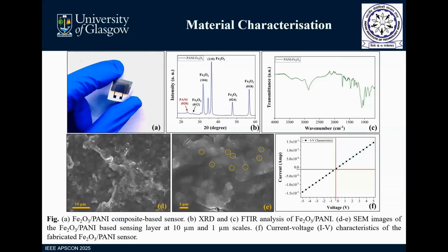In figure A, we can see the original optical image of our sensor. You can see the green part is the electrospun PANI, and the electrode is clearly visible. Figures B and C are the XRD and FTIR analysis, which confirm the presence of PANI as well as Fe2O3 decoration over the substrate. In figures D and E, we can see the PANI, and the dotted circle represents the Fe2O3 nanoparticles over that PANI surface. We also studied the IV characteristic of the sensor, and it shows linear behavior.